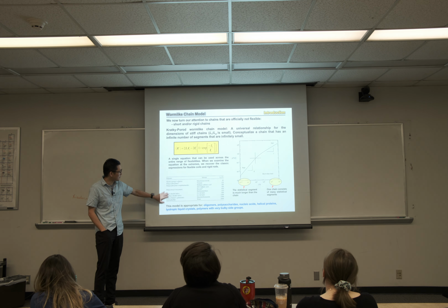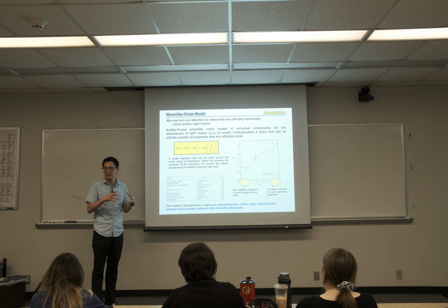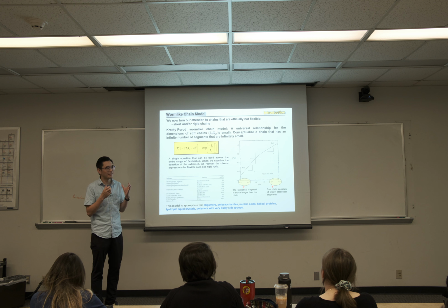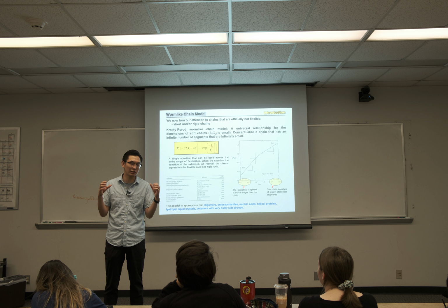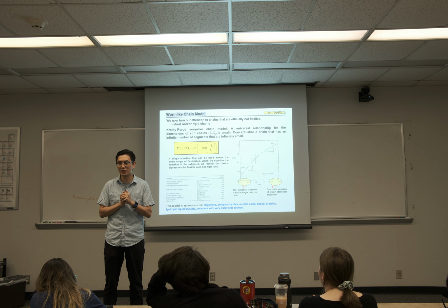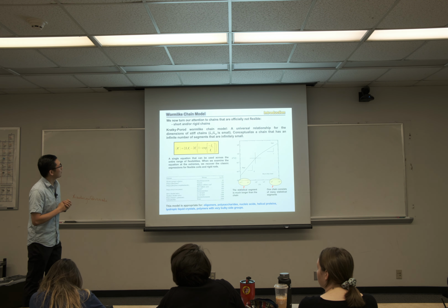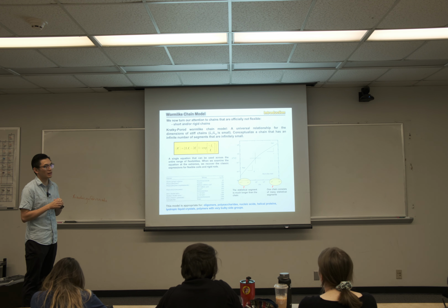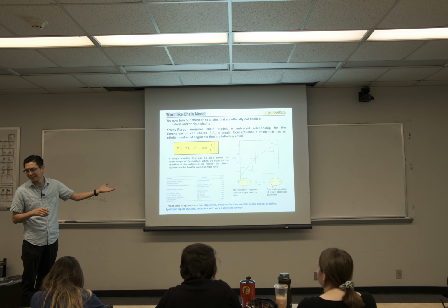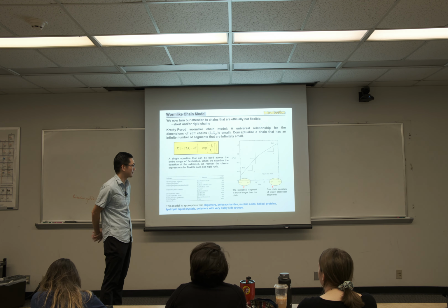Those types of polymers are not easily described by the flexibility of the backbone and chain, because they are typically polymers with a lot of conjugation along the backbone, which means they have large bulky groups such as phenyl rings, such as double bond strands, etc. So the better model to describe those short rigid chains is called the worm-like chain model. As the name suggests, your chain is more rigid and behaves like a worm.